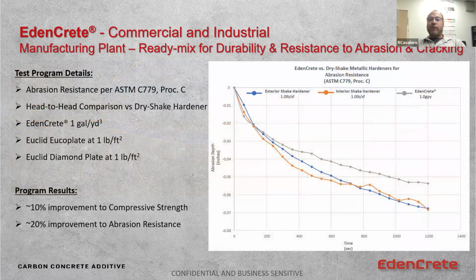So we ran abrasion resistance, that same test I showed you earlier, and we ran it against the Euclid products that Michelin typically use. And we saw that EdenCrete improved the resistance to abrasion by 20% over both of the products. For the product they use in the interior application, EdenCrete is 50% of the cost of the dry shake hardener. Now, guys, we saw this.